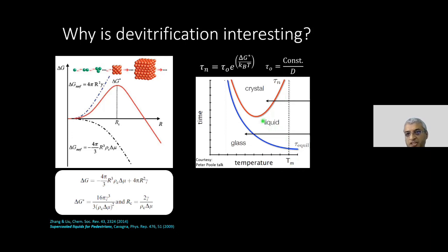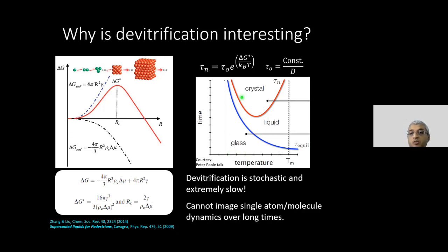So this is the melting temperature. There is an optimal temperature at which you get crystallization the soonest, all right? But the fact that it is non-monotonic means that if I quench the system more and more, I am going to make it harder and harder for it to crystallize, which is why the devitrification that people have basically unearthed has never been observed in situ, okay? It's because it's a very, very slow process. Both of these are like a double whammy that prevent a glass from crystallizing. And of course, there are no experiments in which you can observe dynamics over such a long time scale. So that's precisely what we want to try and achieve by doing a colloid analog of this experiment, okay?